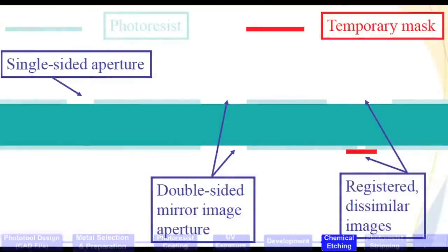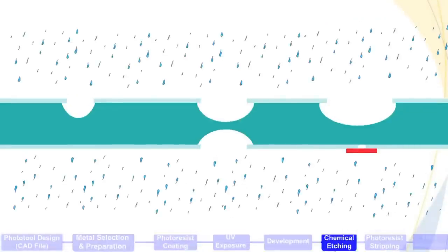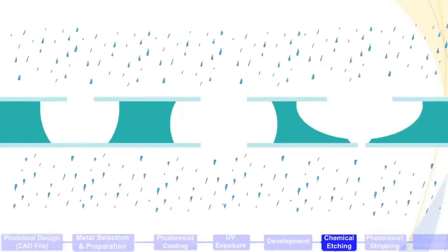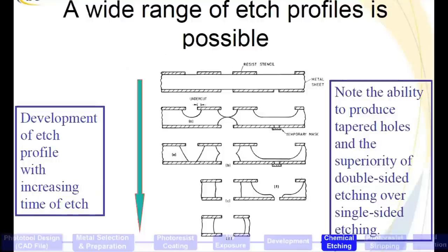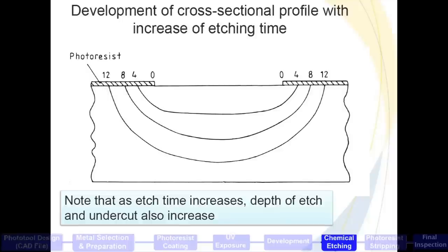One thing to remember when using photochemical machining as a manufacturing process is that as the etchant is dissolving away the metal, the holes and perforations are expanding and the outside dimensions of the part are contracting. And so we incorporate an allowance into the photo tooling so that the apertures and dimensions of the part in question meet the dimensional specifications.